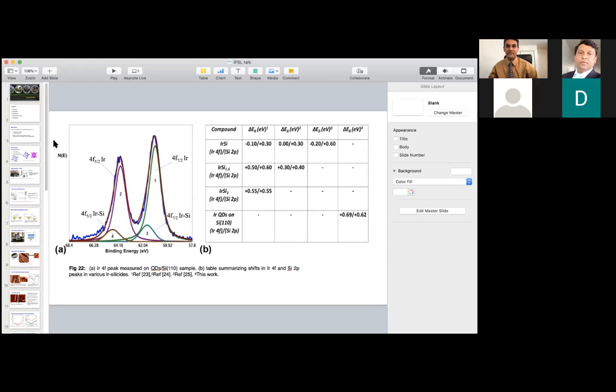Any other questions? Dr. Rasika, you mentioned that when you do the first cleaning process, you are heating it to 1,200 degrees. And then I believe there's a second heating process at 800, to get the reconstructed surface. So for reconstruction, do you cool the sample first? Yes, we have to cool the sample for at least 20 minutes. Okay, so then we need to follow the post-annealing process. Yes, that's a very good question.